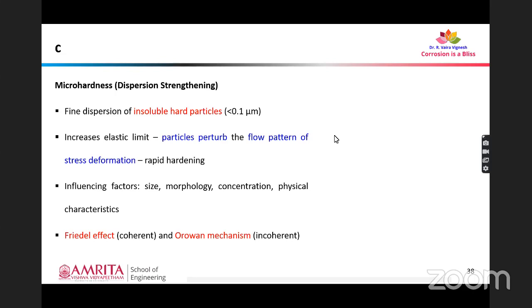What happens in this Orowan mechanism is there will be a dislocation. If a material is subjected to stresses, there will be strain, and that will induce dislocation. That dislocation continues to bend around this hard incoherent particle, and then it will just move on, leaving a dislocation ring around the particle. Why? Because it is difficult for the dislocation to overcome the phase boundary between the host lattice and the incoherent particle. That is why we have enhanced hardness in the composites that are reinforced with nano-phase reinforcement particles of alumina, which is a ceramic phase.